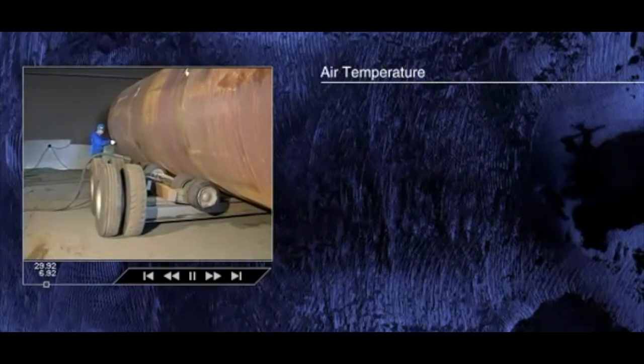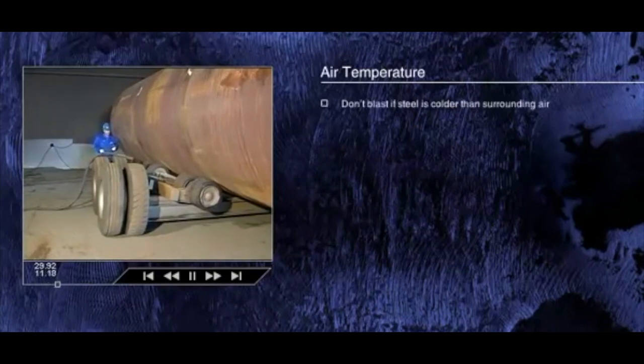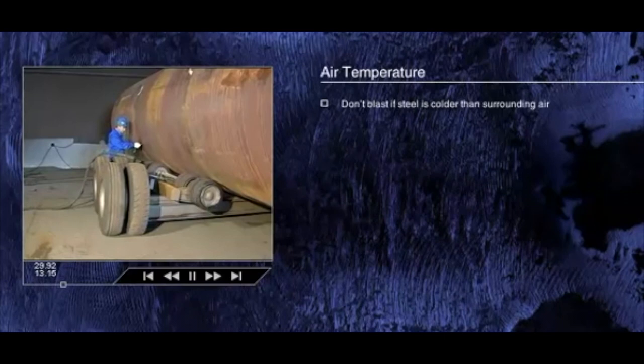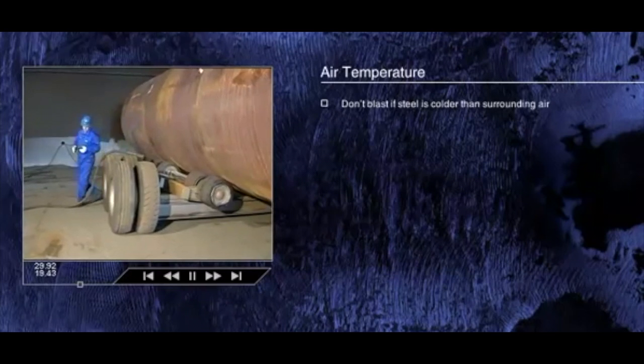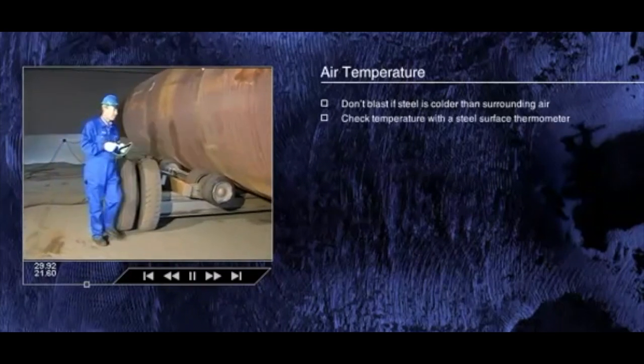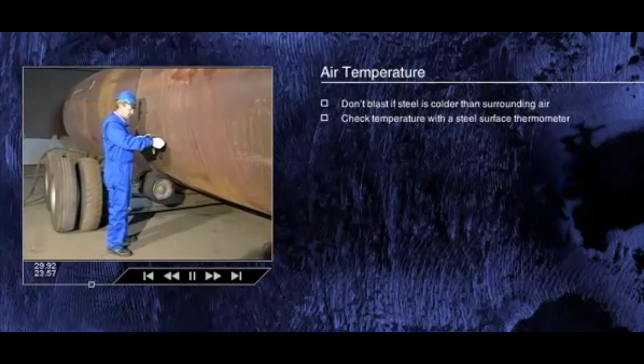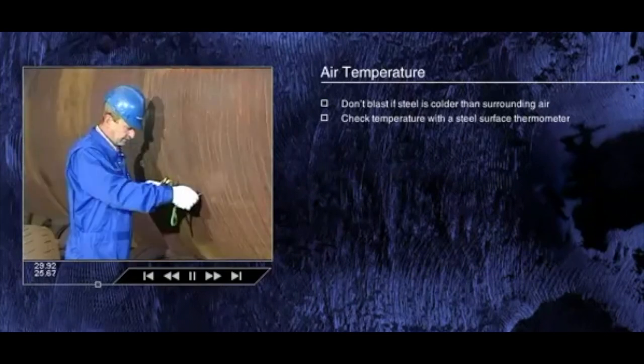It is unwise to abrasive blast if the steel surface is much colder than the surrounding air. Moisture may condense on the blasted surface, causing the surface to flash rust. The substrate temperature may be checked using a steel surface thermometer.